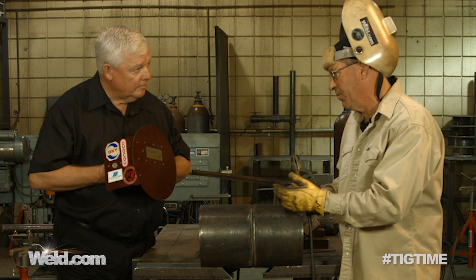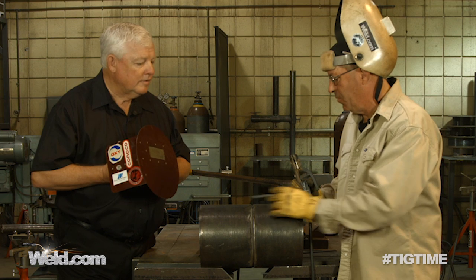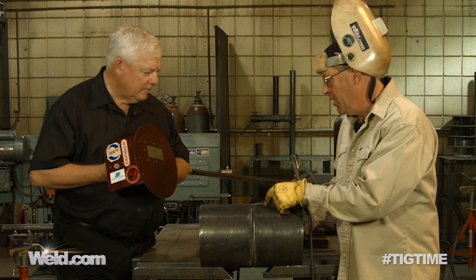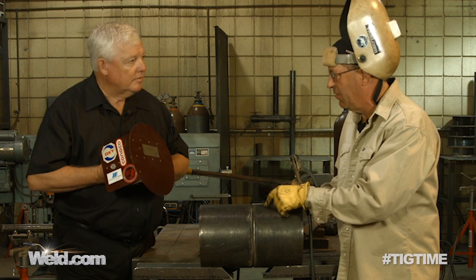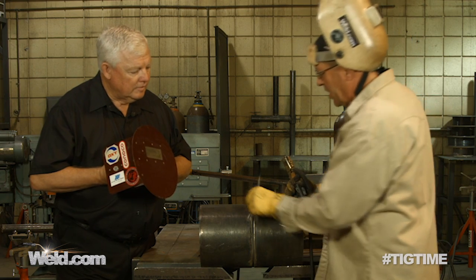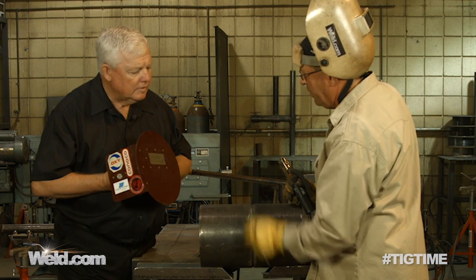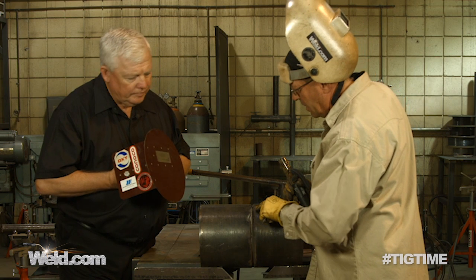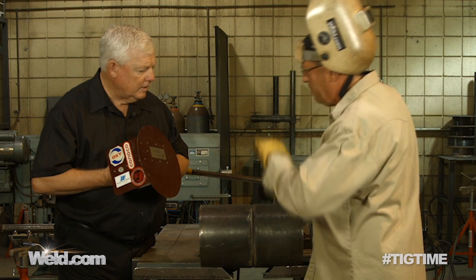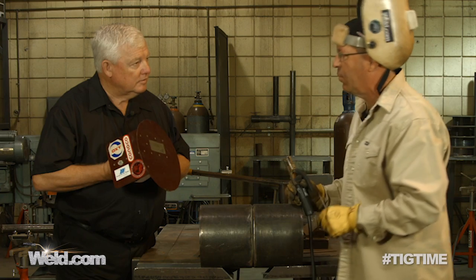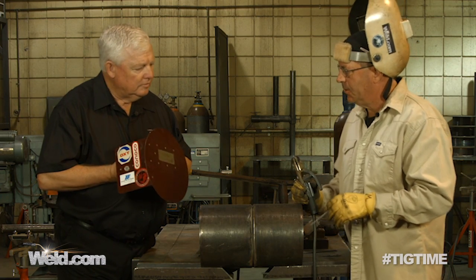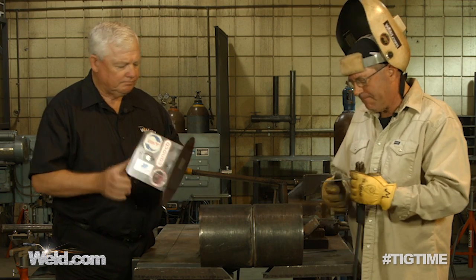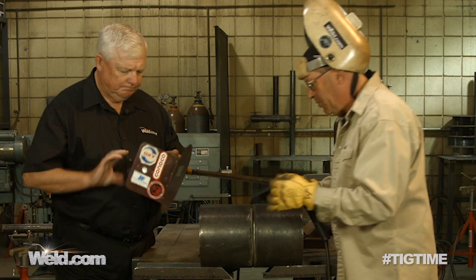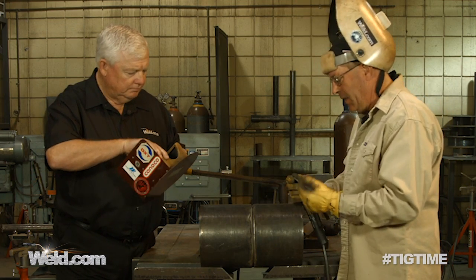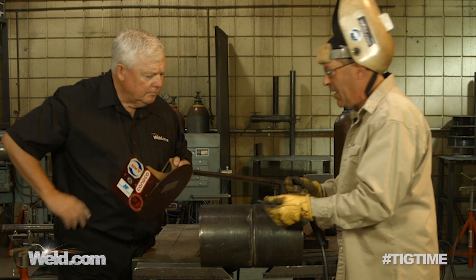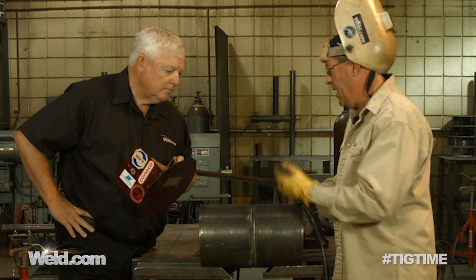The fill pass, I'm gonna slow down a little bit. We want to bring this up to about a thirty-second of an inch or so, flush with the beveled edges. Leave the beveled edges there because I need those as a guide. So when I put my cap in there, I want to be up on top of the pipe and have my allowable reinforcement. Make sense? Yes, it does. Okay. My rod angle, when I'm progressing downhill, I like to run this with, again, I'm running a tight gap. I can run a fairly higher amperage.